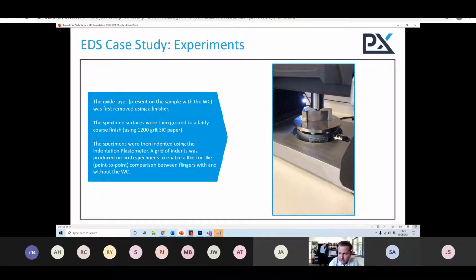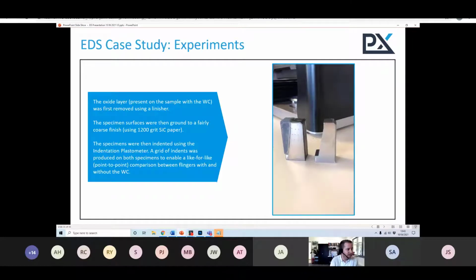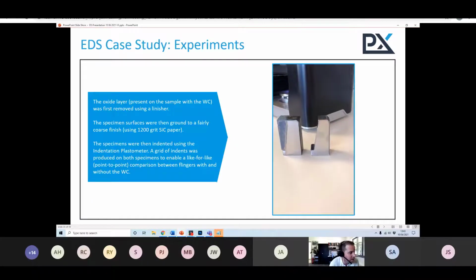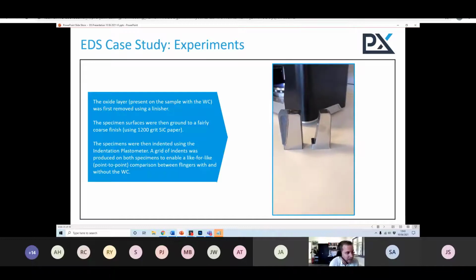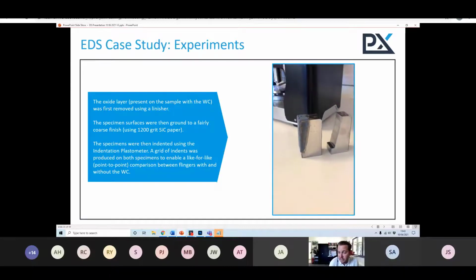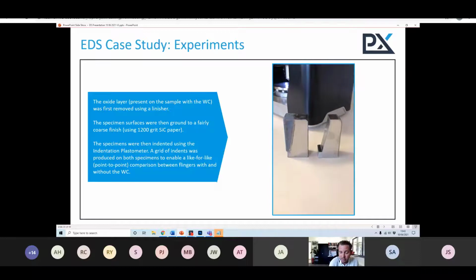I think the video at this stage is being accelerated in time. Once that indent is done, you'll see the profilometer coming across. That now is measuring the shape of that profile. Also takes a minute or so, but it's been accelerated here. And then once you've measured that shape, you can import that into the software package and you can calculate stress strain curves. Okay, so it's very simple. You can see in the video this array of indents that's been created on the as received material and on a material that's been subjected to this high temperature brazing process.